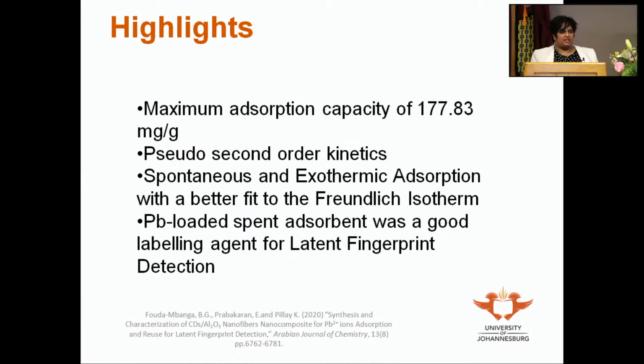So this shows you how we prepared the carbon dots from waste banana peels using a hydrothermal technique. And then we prepared the aluminium oxide nanofibers via a simple sol gel technique. And the carbon dots were coated onto the aluminium oxide nanofibers via a simple adsorption technique. So again, you see a reasonable adsorption capacity, but again, the highlight was that the lead-2 loaded spent adsorbent was a good fingerprint detection agent.